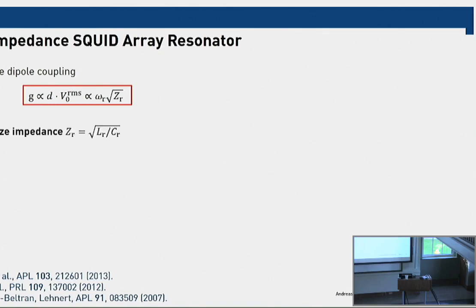And you know that the impedance is given by the square root of the characteristic inductance of the resonator divided by the characteristic capacitance. So if you make a resonator with a very large inductance and a small capacitance, you can enhance the size of the vacuum fluctuations of the electric field component. And you could do the reverse if you don't want to electrically couple, but magnetically couple. If you wanted to couple to a single spin strongly, you would also not use a 50 ohm resonator, but you would use one where the inductance is small and the capacitance is very large. And that has also been looked at.